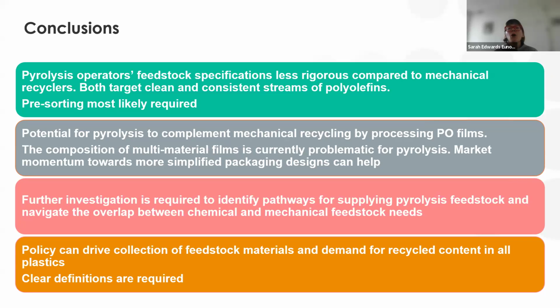The potential of pyrolysis to complement mechanical recycling, specifically for the processing of polyolefin films, was highlighted throughout the research by those chemical recyclers we spoke to, and the composition of multi-material films is currently problematic for pyrolysis. So we talk about multi-material, multi-layer, but what they're looking for is multi-polyolefin mix materials, with some of the barrier layers that might be needed on some packaging material removed. And then there needs to be greater investigation to identify pathways for supplying facilities with feedstocks, which we've touched on a little bit today, but clearly more work needs to be done so that these technologies can be complementary. And policy is probably going to be critical in the supply of material moving forward.